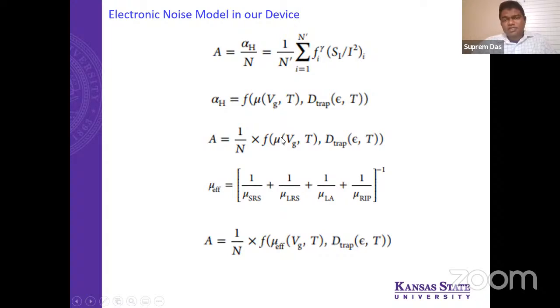But we know also mobility has different origins. Mobility can be from different sources. For example, mobility can be from your intrinsic mobility, or it can be from long range scattering. This is short range scattering. This is long range scattering. This is your longitudinal acoustic phonon, and this is something called a remote interfacial phonon. So in the case of graphene, these are the typical dominating factors that can change your mobility. So we must also consider that. So in principle, this mobility should be your effective mobility, which is again dependent on all these factors.